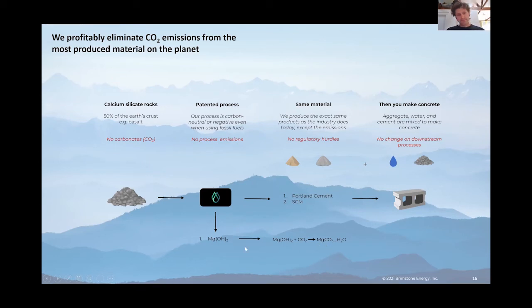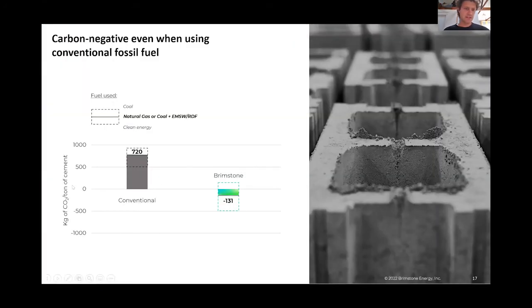So it turns out that even for a conventional fuel mix, this magnesium waste product leads to a carbon negative cement. So that's what this graph shows here. Here's kilograms of CO2 per ton of cement on the y-axis. On the x-axis you have conventional cement versus brimstone cement. Here's pure coal, which almost nobody uses. In the middle line is either natural gas, or a mixture of coal plus refuse derived fuel or engineered municipal solid waste, so things like tires or solid waste pellets. And then the bottom dashed line is clean energy.